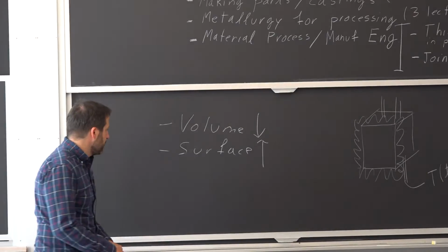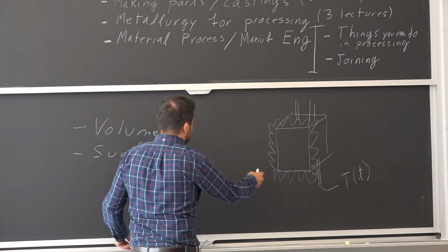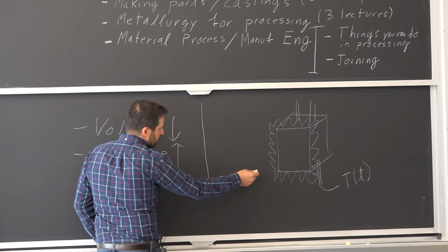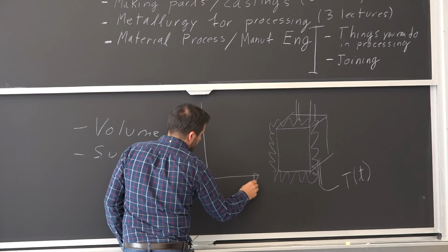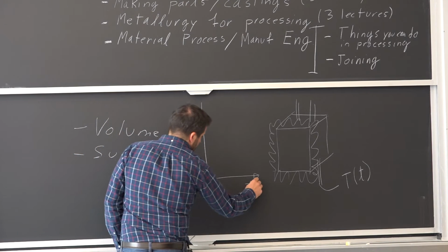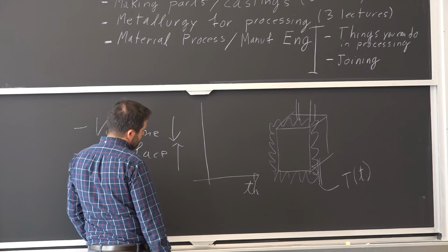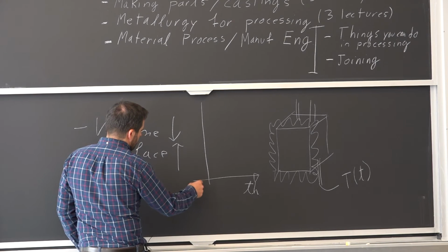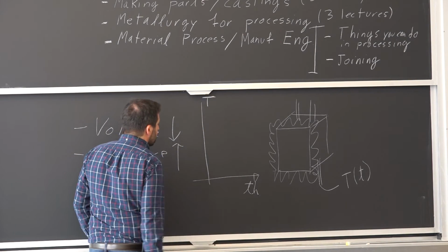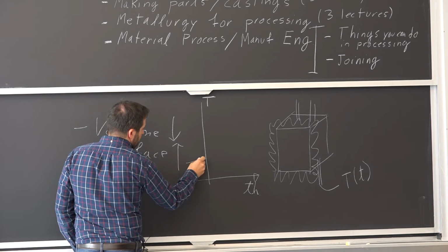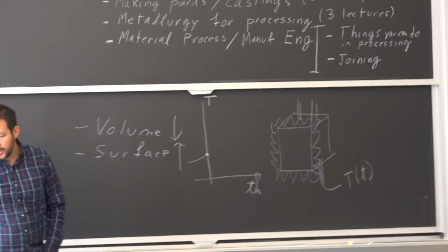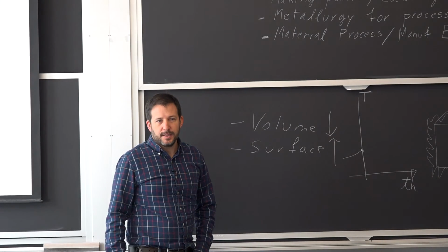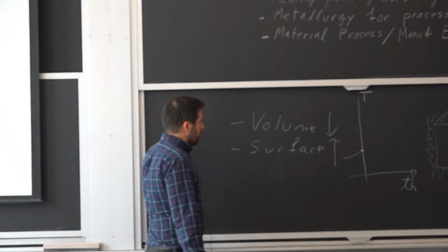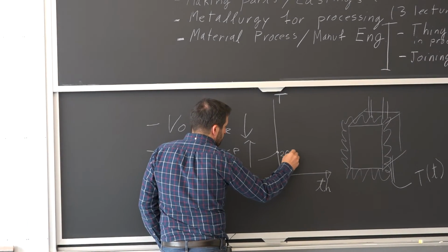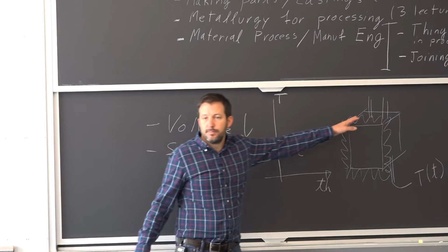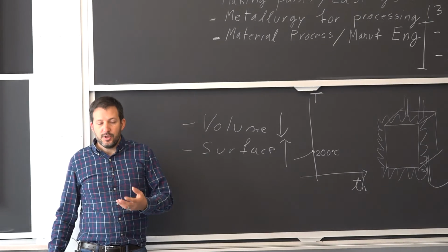Maybe the only thing I'll say there, because we talk about casting that is relevant, is when you look on a plot here, let's say that's the thickness direction for the deposit. So TH, not to confuse it with time. What happens is you're going to have a temperature of your mold. In our case, that's the copper here. That's fairly low. Not that I would touch it, but it doesn't melt, right? We're looking at maybe a couple hundred degrees is all it does to this side, because of the cooling system, mainly, and also when you solidify, you create an interface.